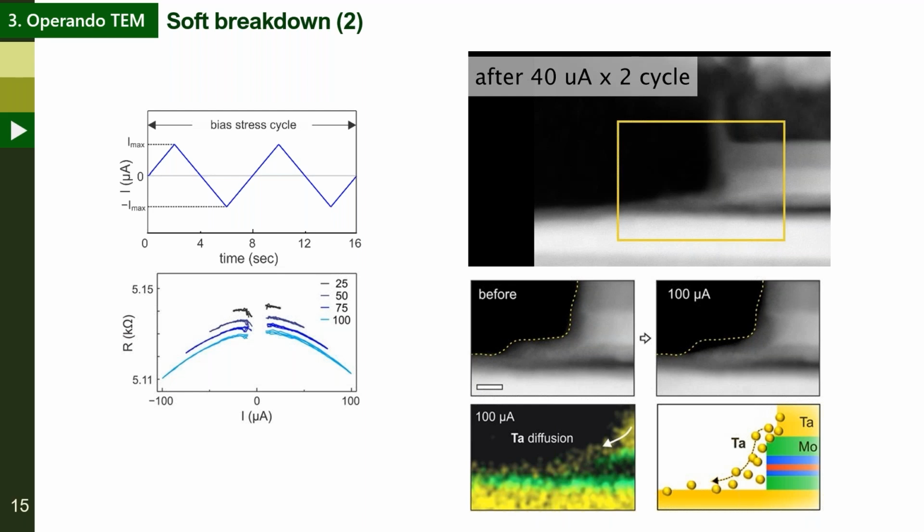So as I said before, in addition to the formation of the pinholes, significant degradation happens near the edge region in the nanopillar. As illustrated in this image, it shows the tantalum region diffuses further, and then it creates the connection between the top and bottom layer.